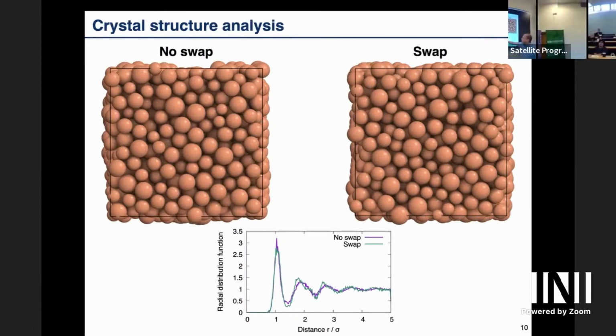Yeah, so what we do here is a radial distribution function. That's essentially the distribution of pair distances in our sample. And they always look like this. Because they are hard spheres, there are no spheres at short distance. There's a first peak, these are the first nearest neighbors, there are second nearest neighbors, and then it oscillates out and becomes constant at 1. This is how it looks for a glass or for a liquid, it always looks like that.